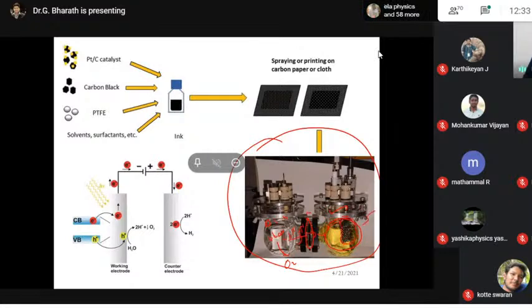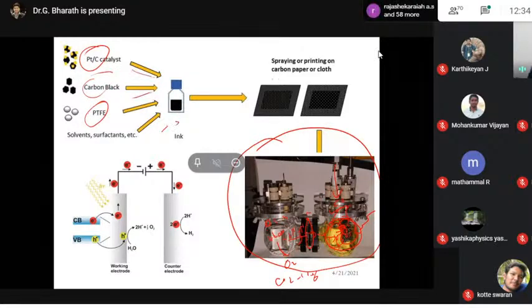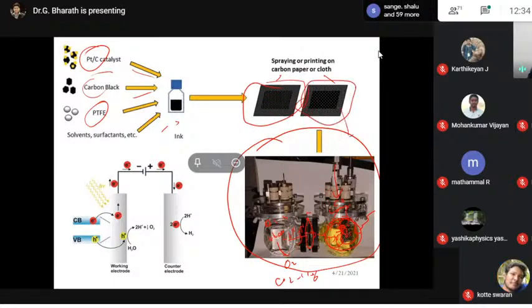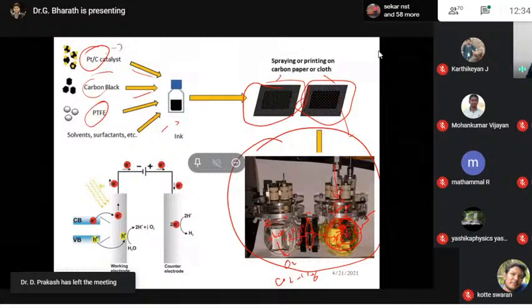On this photocathode, we apply some sunlight, which produces electrons, and we also supply some electrons. So enormous electrons are available on this side, and H plus ions also reach this chamber. Then when we supply CO2, it goes through the electrolyte and is converted into CH3OH. For the electrode fabrication, this is just an example: this is your active material, and you use some carbon black or a binding agent, mix it and make it like an ink, and then just spray or print it. Then you get the complete electrode, which you can place as your working electrode. That's it, this is a photoelectrode. Suppose people use platinum carbon.